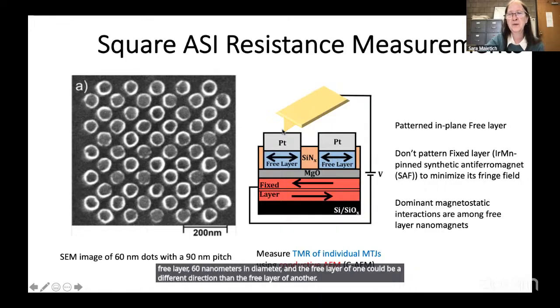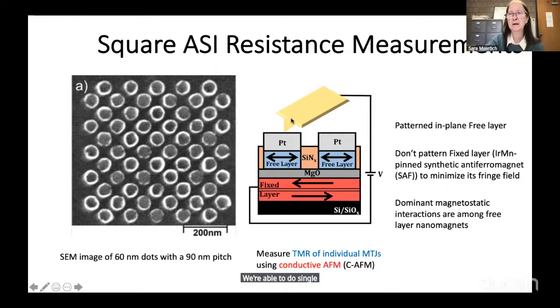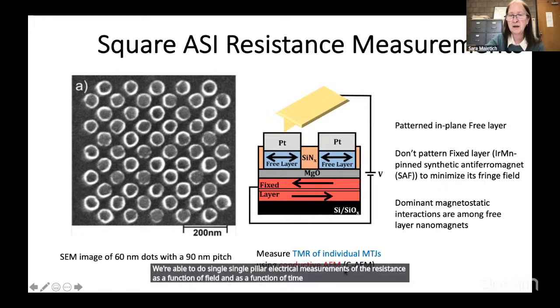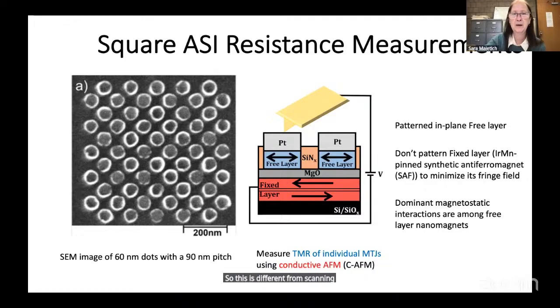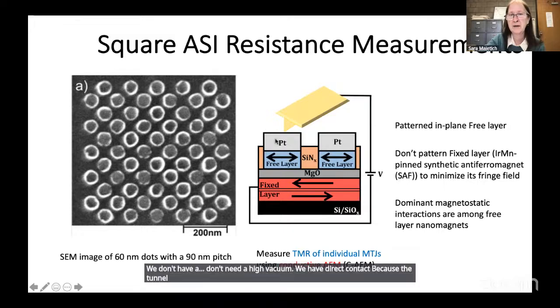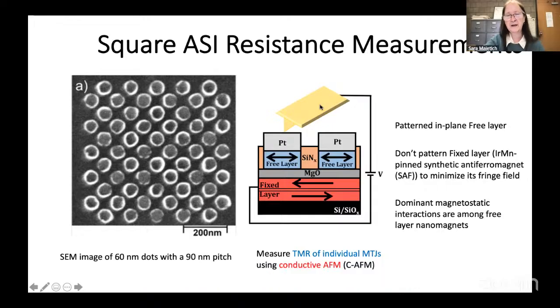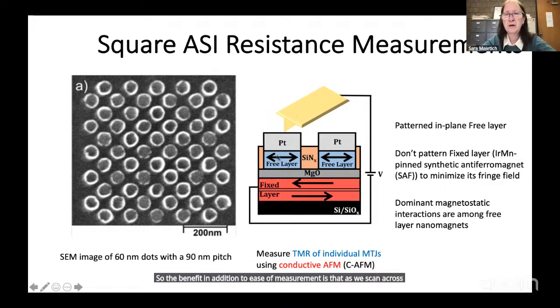We're able to do single dot, single pillar electrical measurements of the resistance as a function of field and as a function of time using conductive atomic force microscopy. This is different from scanning tunneling microscopy because we can do this in air. We don't need a high vacuum. We have direct contact because the tunnel barrier is not the vacuum, the tunnel barrier is built into the device. So the benefit, in addition to ease of measurement, is that as we scan across the devices, if we go from a conducting region, we can measure the resistance dynamics.